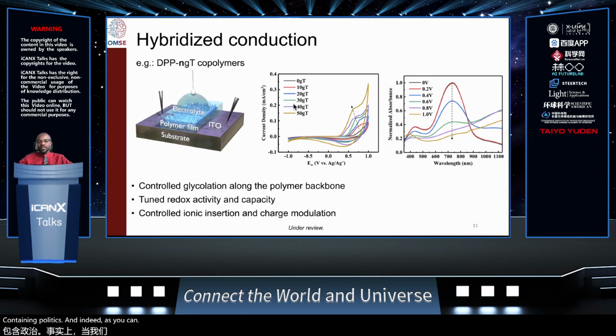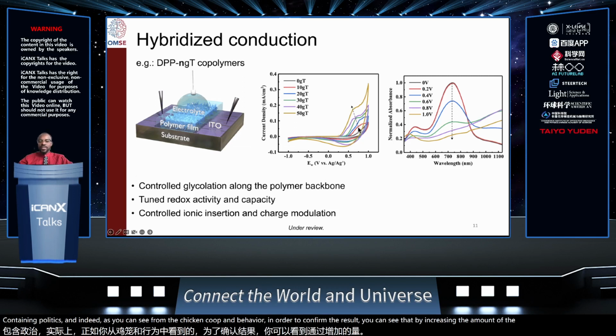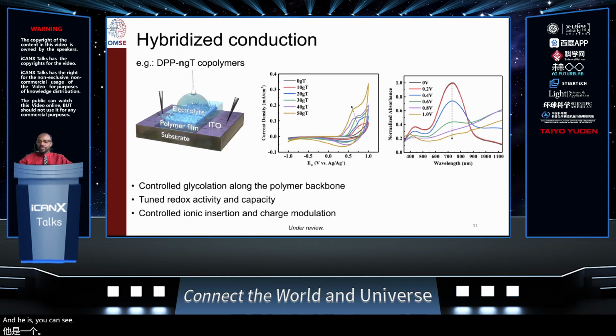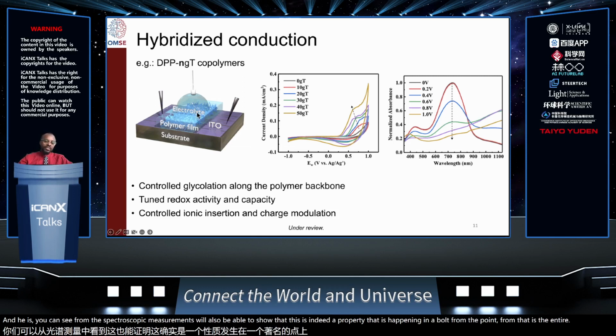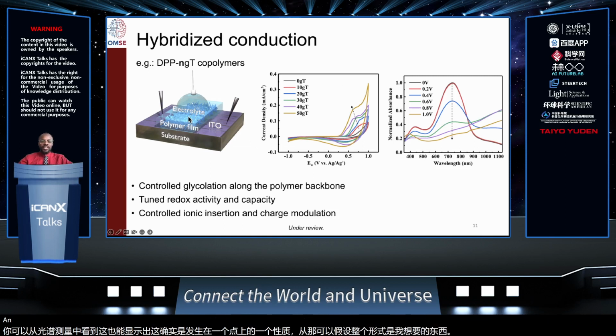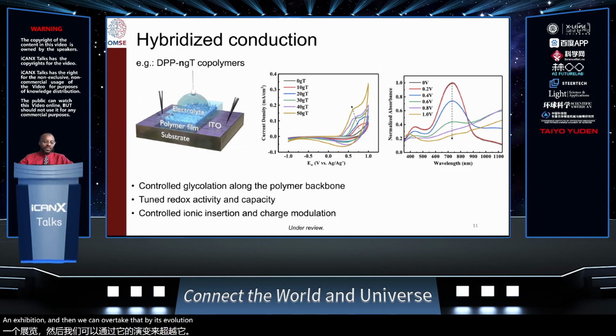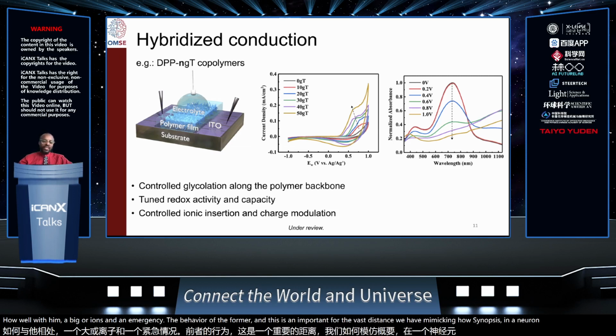Indeed, as you can see from the electrochemical results, by increasing the amount of polar groups that we have, we are increasing both the capacity and the redox activity of our polymers. And as you can see from the spectroscopy measurements, we are also able to show that this is a property that is happening in the bulk of our polymer. That is, the entire polymer film is able to uptake ionic species, and we can detect that by its absorption spectra. This is exciting because now we have some control in terms of how well we can uptake ions and modulate the behavior of the polymer. This is important for the above discussed way of mimicking how synapses and neurons communicate in our body.